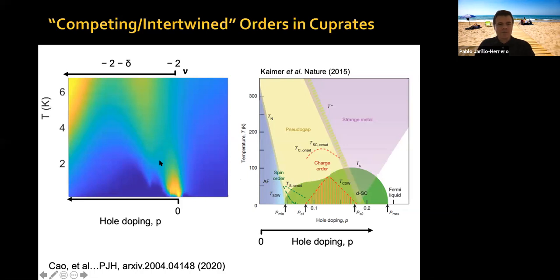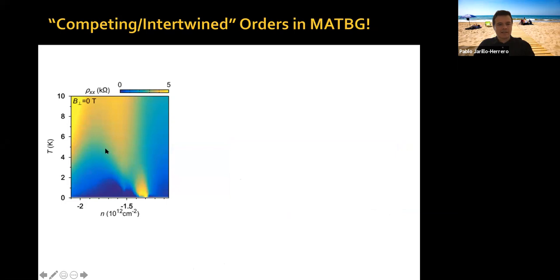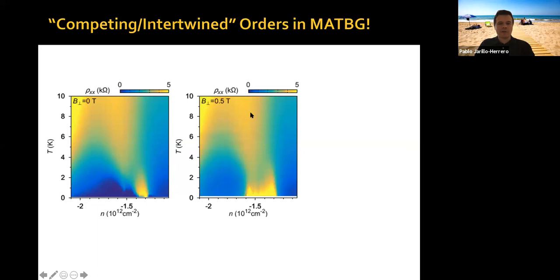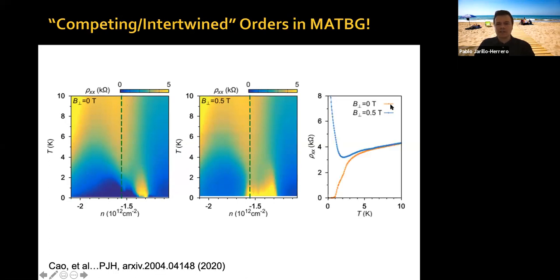Now, one thing that we can do is take these data, which are at zero magnetic field, and say, okay, there seems to be something competing with superconductivity. Why don't we suppress superconductivity and see what's really underneath? So this is the correlated insulator state, which is quite weak for these devices. It happens only near zero temperature, and at about 10% doping from it, you have this feature. If we apply a small magnetic field, then you see the following. This ridge develops a strongly insulating state at the lowest temperature once superconductivity is gone. If I take this trace here, at this particular doping, you can see that at zero magnetic field you have superconductivity. At finite magnetic field, you have an insulating state for the exact same doping.